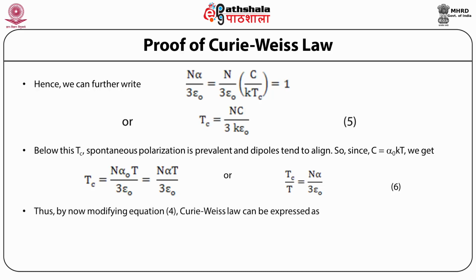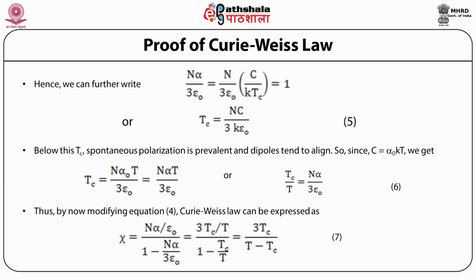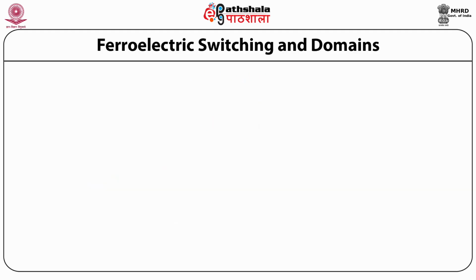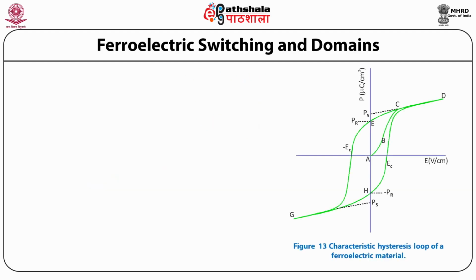Thus, by modifying the expression, the Curie-Weiss law can be expressed as susceptibility, that is chi, is equal to n alpha by epsilon naught divided by 1 minus n alpha upon 3 epsilon naught, which comes out to be 3 Tc divided by T minus Tc. Ferroelectric switching and domains.